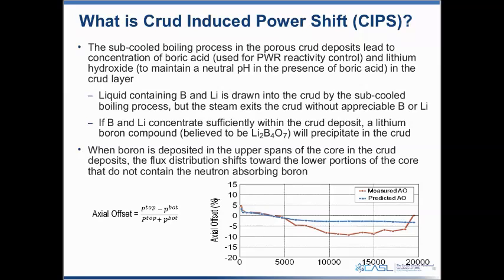Typically in an operating PWR, we're using boric acid for reactivity control, which would result in an acidic type coolant that can increase corrosion rates on system surfaces. So we add lithium hydroxide as a buffer to maintain a near neutral pH in the presence of the boric acid. So when we have liquid containing boron and lithium, and it gets drawn into the porous crud by the subcool boiling process,